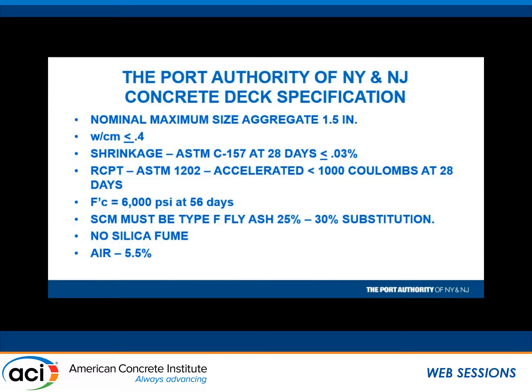You have ASTM C157, you have the ring test. How do you do the C157 test? Do you follow ASTM C157 to the T? Well, if you do, I'm not quite sure what you're getting. So in our specification, we say you strip it in 1 day, and after 1 day, you get the initial reading, and then you dry cure it for 28 days, and that's how we want you to measure shrinkage.